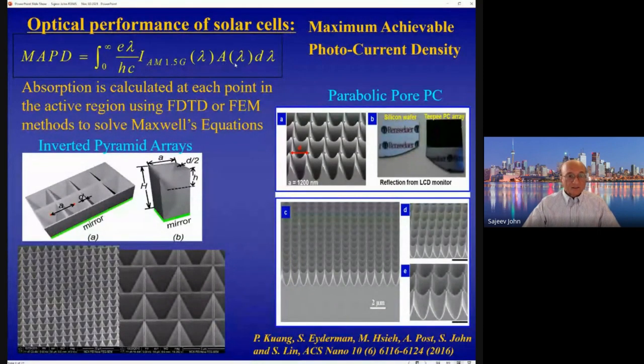It's something between 0 and 1, dividing by hc over lambda, which is the energy of a photon at wavelength lambda. That gives the number of photons at that wavelength, and then multiplying by the electronic charge, which then converts that light into an effective photocurrent density. And this absorption is something that we calculate by numerically solving Maxwell's equations inside the structure using either a finite difference time domain or FEM method.